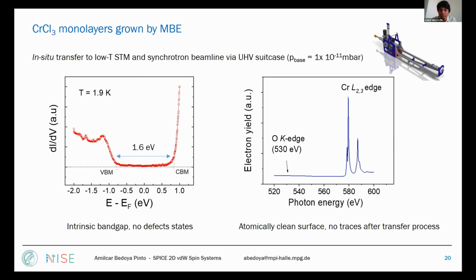So then we transfer our sample with our ultra-high vacuum mobile suitcase to the low temperature STM. And here we can see that at very low temperature, by scanning tunneling spectroscopy, we can infer a band gap of 1.6 eV. And most importantly here is that we have a gap close to the intrinsic band gap and no defect state whatsoever in our film.